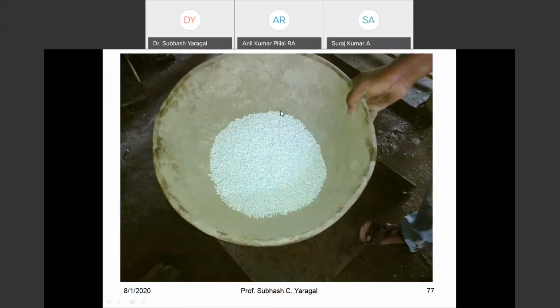You can use these pellets at about 10 to 15% without compromising much on the quality. Even if the strength comes down, you can identify where you can use these lightweight concrete products for non-structural applications. So that way we have shown that even plastic pellets can be used scientifically in some products.